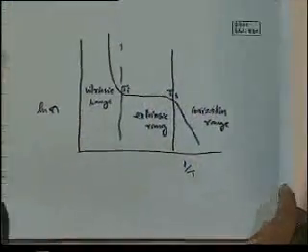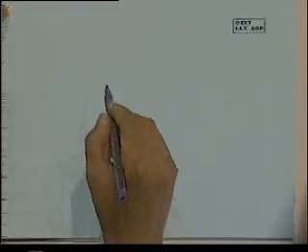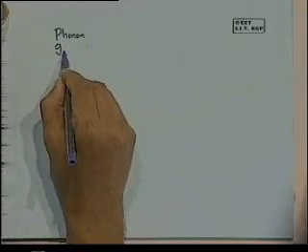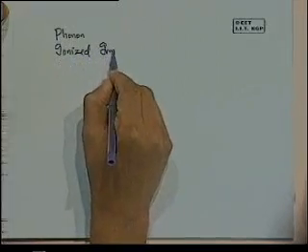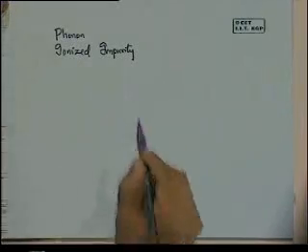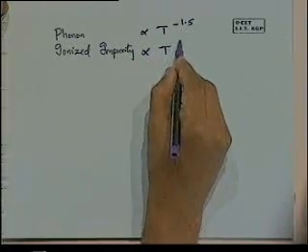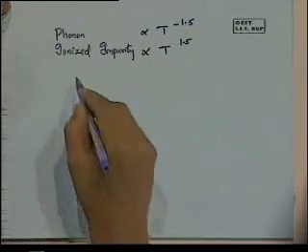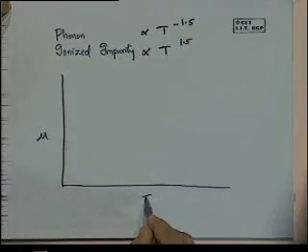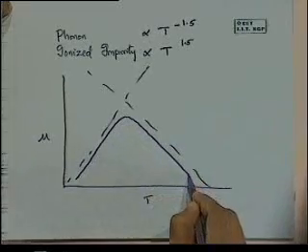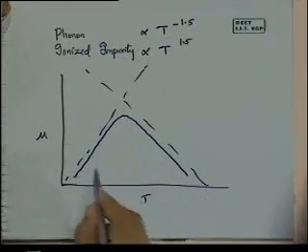We had a relationship relating N and T, and then we looked at various mechanisms affecting mobility. The two we focused on were phonon scattering (lattice vibration scattering) and ionized impurity scattering. Each had a different temperature dependence: one proportional to T to the power minus 3/2, the other with T to the power plus 1.5. When we plot mobility versus T, we see two curves, and the overall behavior is approximated by Matthiessen's rule.